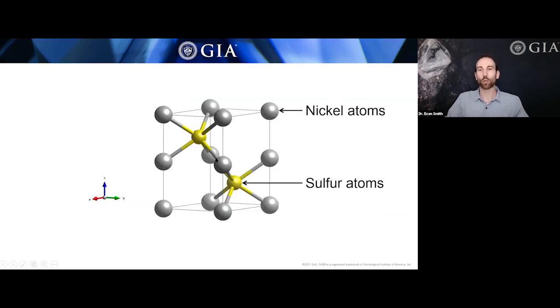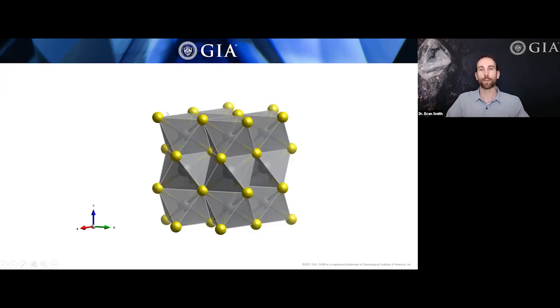So if we look at that again in more detail, this is what its crystal structure looks like. This is the unit cell. So this is the smallest diagram you could draw that still contains all the relevant structural information to describe this material as a crystalline material. And it's made up of nickel atoms, and in yellow here, these are sulfur atoms. And I've also drawn it in a slightly different way, where we've built polyhedra. So here we've got, again in gray, the nickel atoms, and each nickel atom is bound to 6 sulfur atoms, and this defines a little octahedron. So you can think of this mineral as being built up of all these tiny octahedron shapes that are nickel atoms surrounded by 6 sulfur atoms. And these octahedra are stacked up face to face along the C-axis of this mineral.